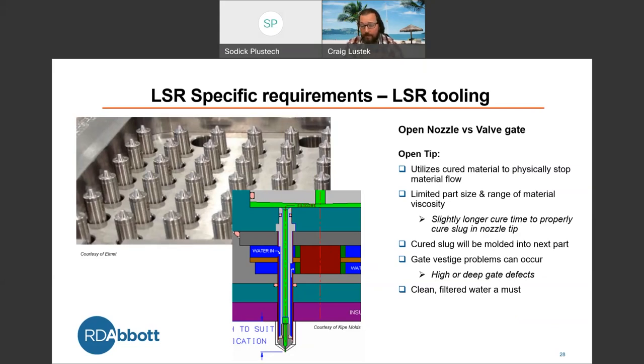Also, you can have gate vestige problems, high or deep gates, and clean filtered water is definitely a must with this. As small as these nozzles are, any small little particulate or foreign debris can clog up one of these water jackets. And now, instead of running at 100% on a nozzle, you can only be flowing 80%. And that could create problems as there's really no way to dial these nozzles in.